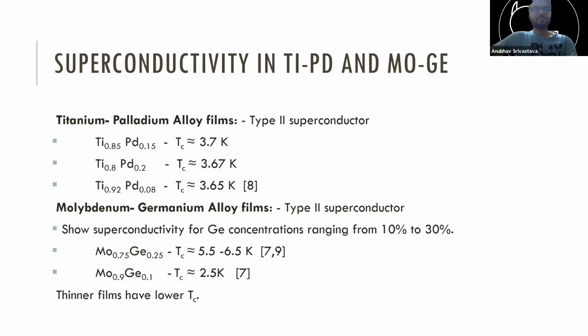Yeah, so for molybdenum germanium, you need germanium's concentration in the range of 10 to 30% if you want superconductivity. And if the concentration is above that, then you won't find superconductivity. So that is again something that is very important. The exact ratio of the concentration is something that you will have to try.